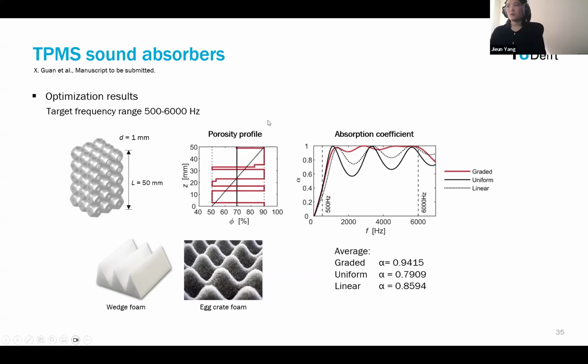And we also compared the result when we conduct optimization for the uniform porosity, which means that we have the uniform porosity over this whole thickness, and then that was this value around 70% porosity. And then we also compared the result with the linearly changing porosity profile from 50% to 90%. And then this is the absorption coefficient. So this red line is the graded optimal one, and these dotted lines are for the linear porosity grading, and this black solid line is for the uniform porosity.